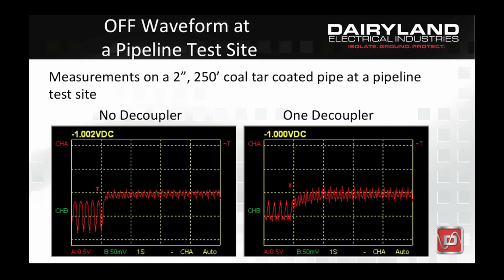This measuring error has not been an issue on coal tar coated pipelines in the field because those pipelines are considerably larger in diameter and longer in length with a lower RC time constant. But this example shows that this measuring issue can still occur with lower resistance coatings if the pipeline is very small in diameter and very short in length.